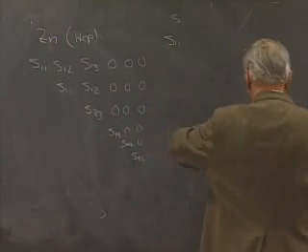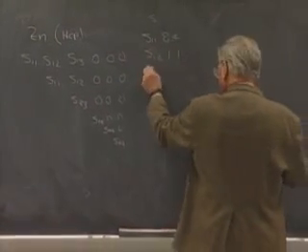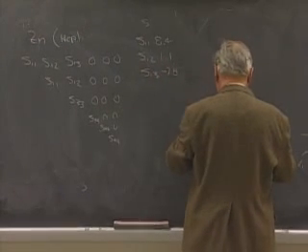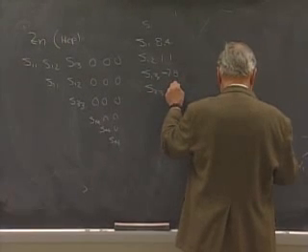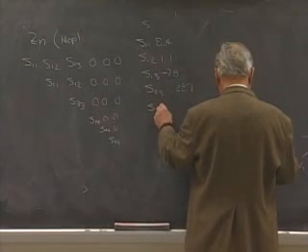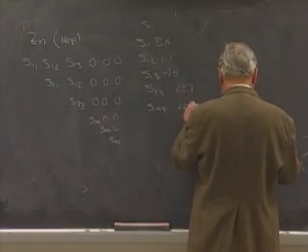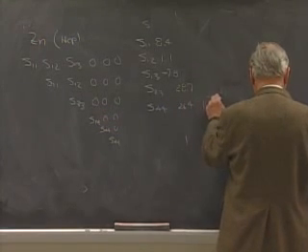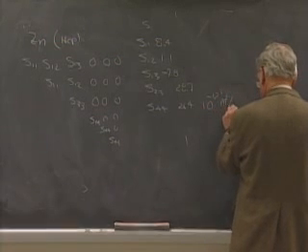And the values of these specific compliances are 8.4 for S11, for S12, 1.1, for S13, minus 7.8, for S33, 28.7, for S44, 26.4, and these are all in units of 10 to the minus 12 meters squared per Newton.